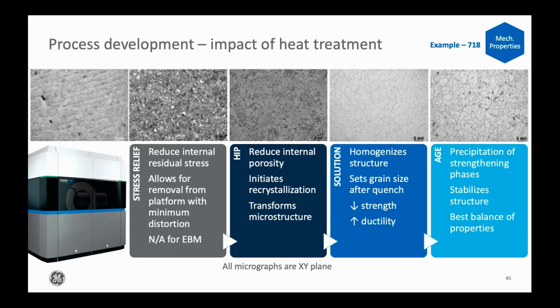Kind of showing that development and why we think we're getting that better tensile capability than casting. You start with that very layer-wise process, and for the parts that were built off the Atlas machine, they would follow this relative thermal process map, which started with a stress relief, followed by a HIP to reduce any internal porosity for fatigue, and then the typical solution age that you would see in 718.